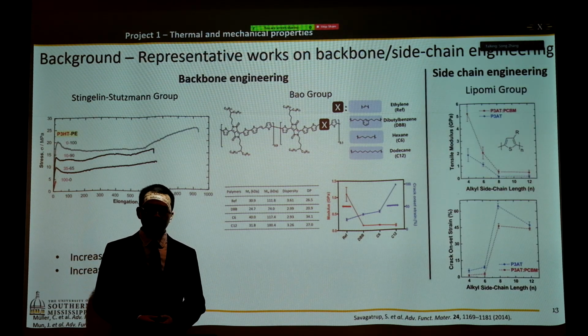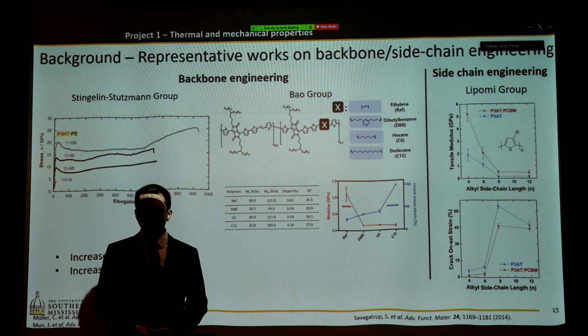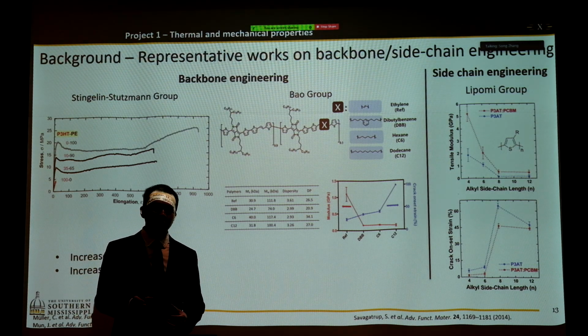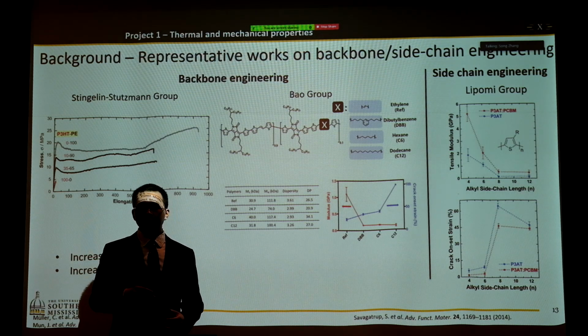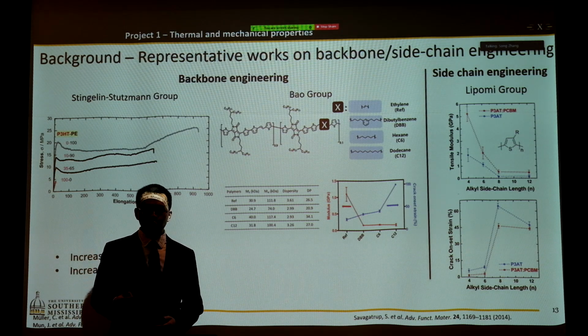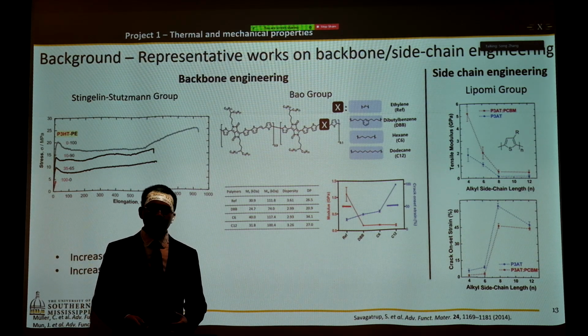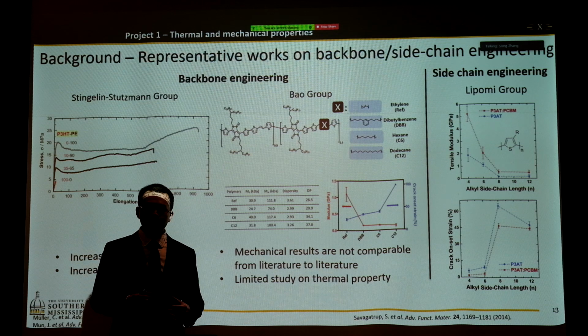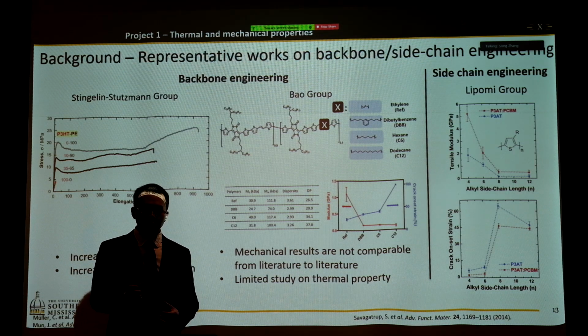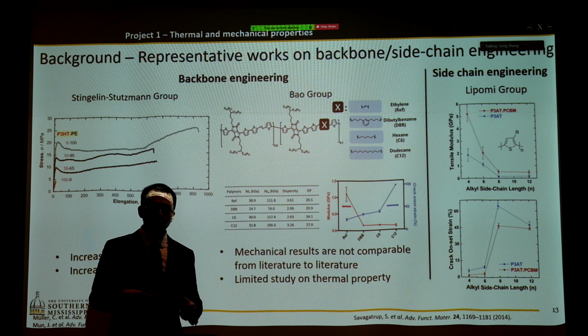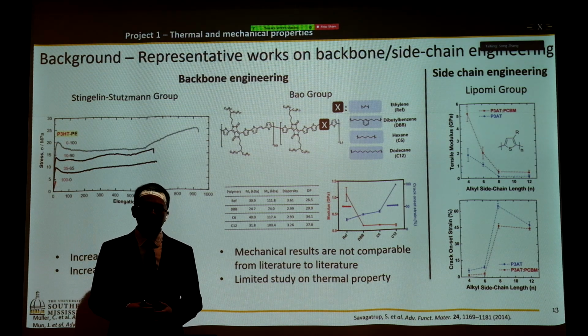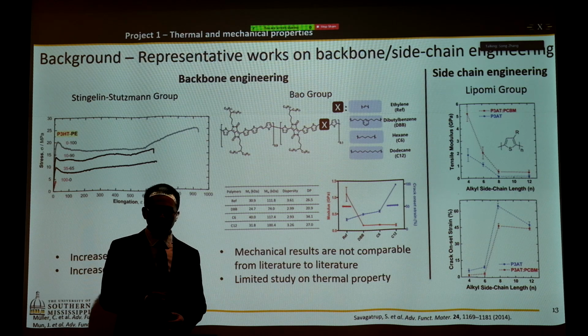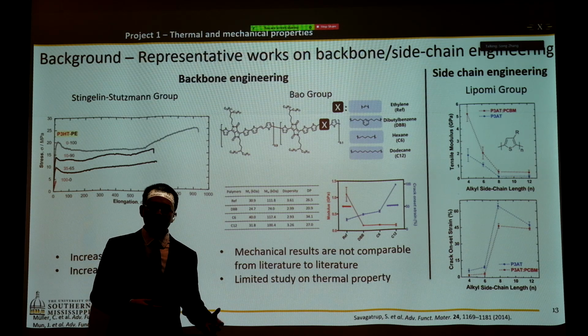Another similar technique was employed by Dr. Lipomi's group. So by engineering the sidechain of polythiophene, they found that increased sidechain length is going to lower the elastic modulus and improve the crack onset strain. However, there are some shortcomings of these results, because by using the film-on-elastomer method, their elastic modulus measurements were not comparable from one group to another or from literature to literature, because the strain rates they are using are very different. And that makes a problem. We cannot systematically compare one polymer from another.